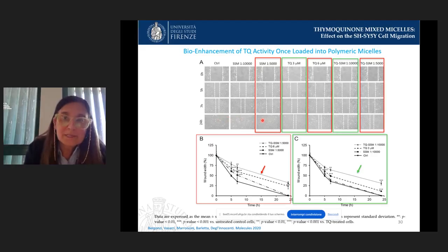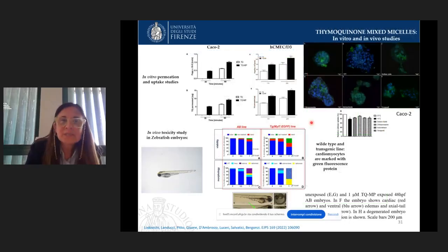We tested also the mixed micelle without thymoquinone to verify the influence of the empty carrier on cell migration, but no effect was evidenced. Thymoquinone reduced the migration at two different concentrations, but the efficacy of thymoquinone is enhanced when it is present inside the mixed micelle, because the scratch closure is bigger in this case, in the presence of the formulation, with respect to the drug alone. So also in this case, the nanoformulation improves the bioactivity of thymoquinone in this in vitro test.